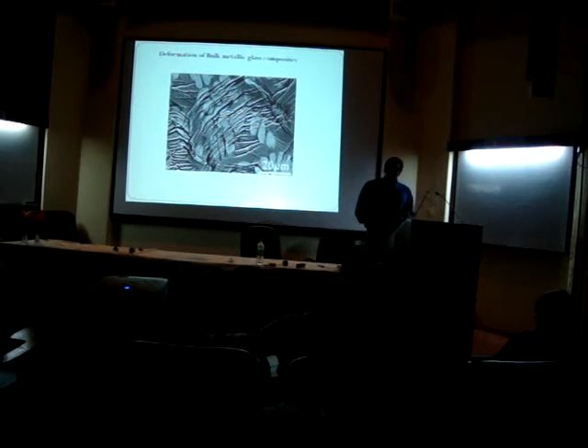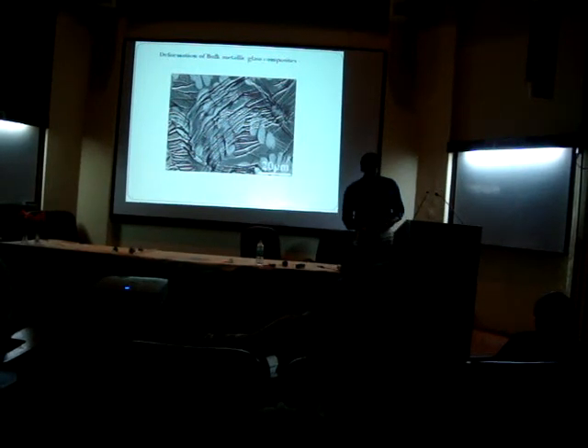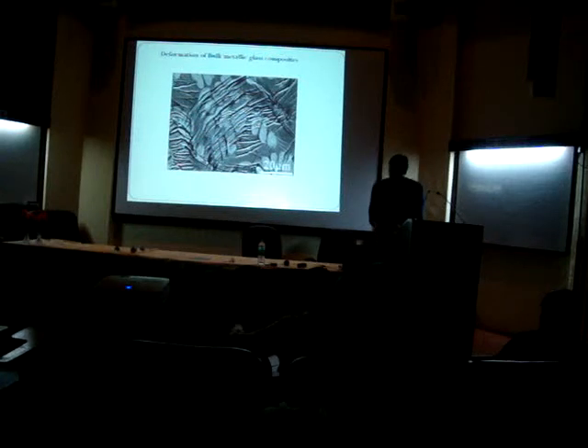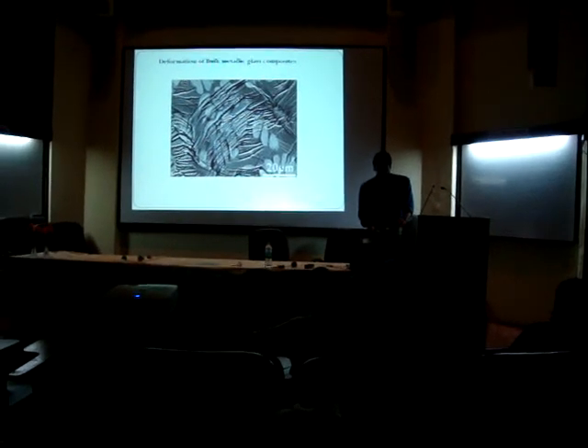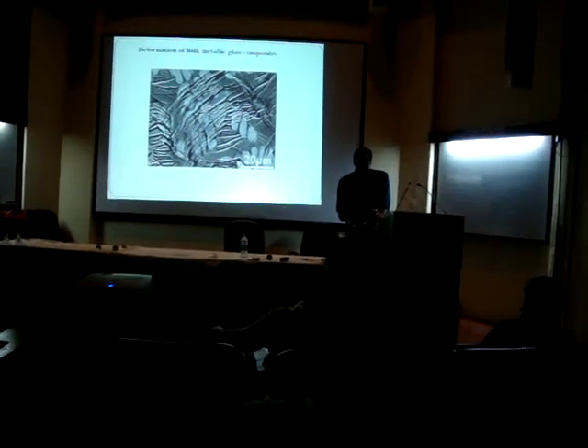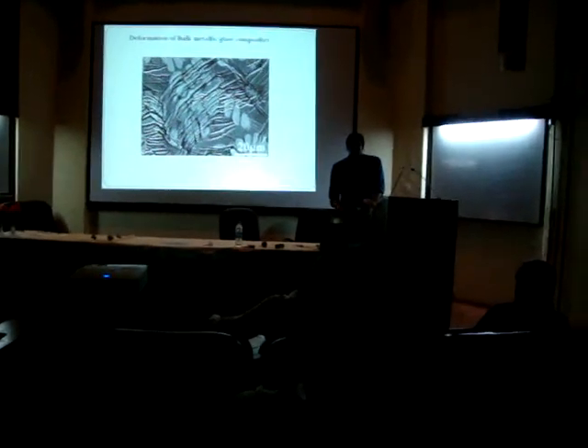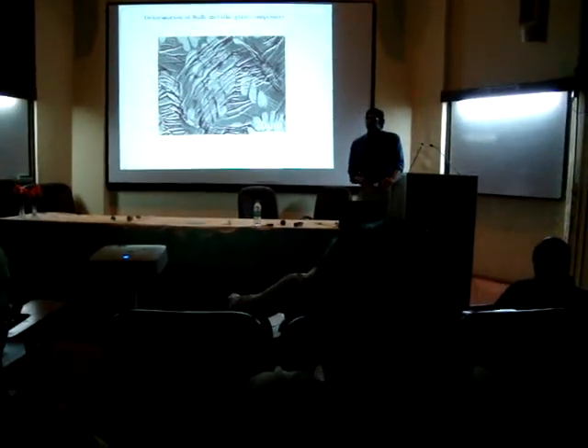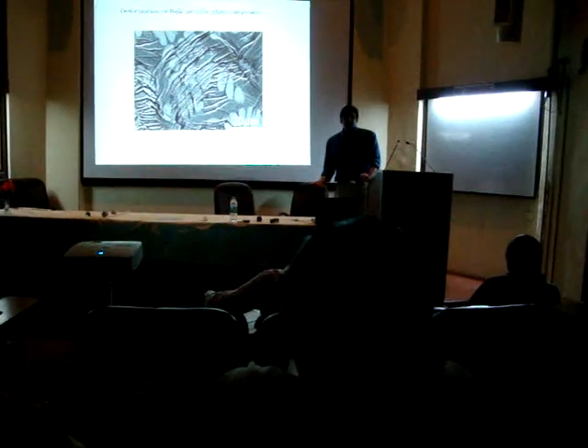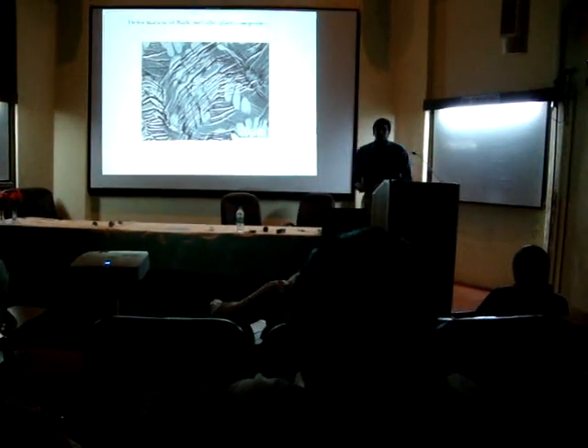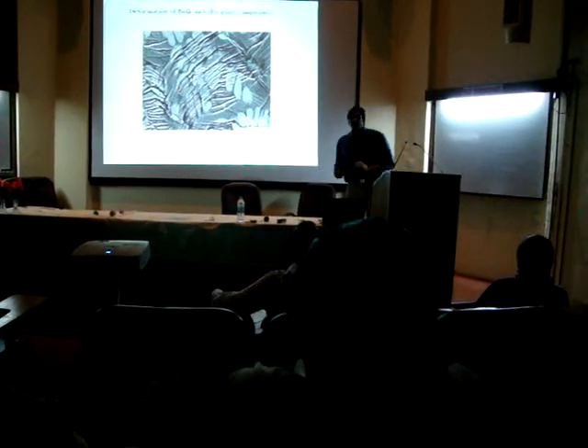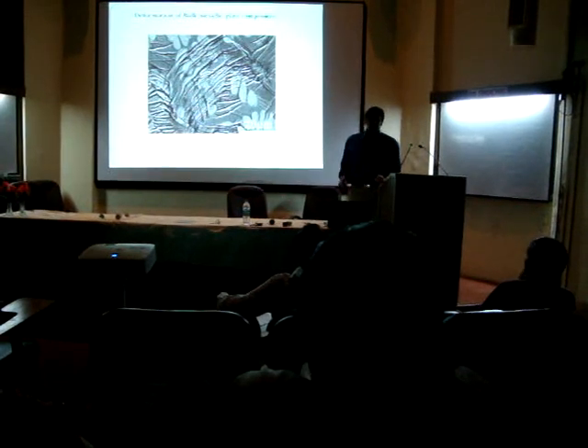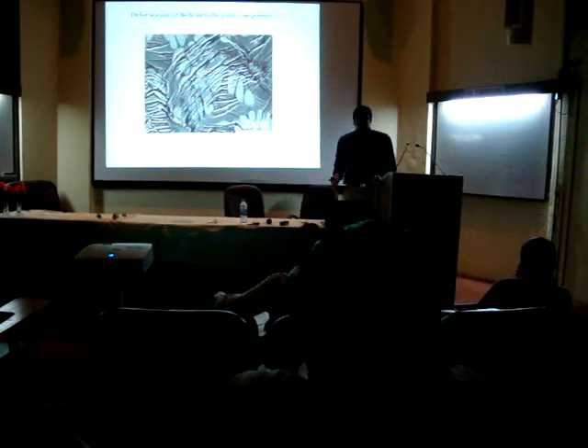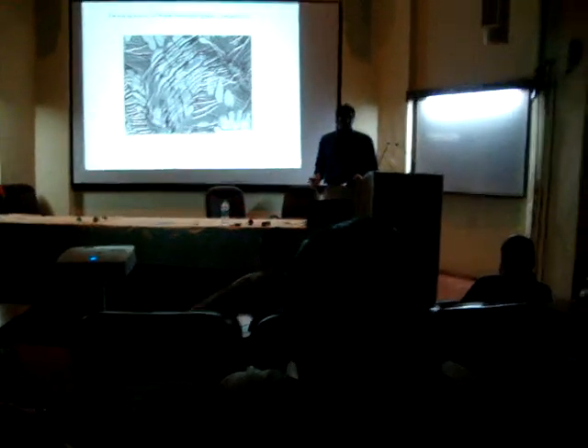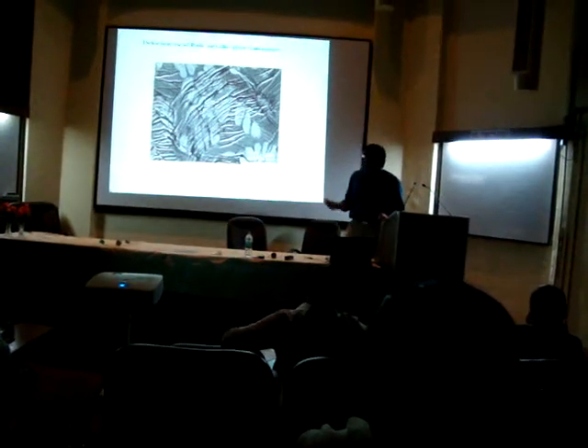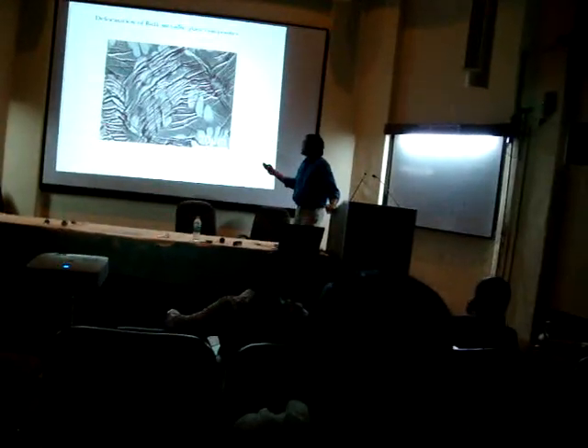Now, we move on to the last part of my talk, and I should talk about another way of toughening glasses, which recently became popular, where you introduce a second phase, a ductile phase, and this ductile phase promotes shear banding, which improves its tensile integrity. Earlier we saw that if you pull a BMG rod in tension, it will break catastrophically without any sign of ductility. But when you add a second phase, this can nucleate shear bands, deflect them, multiply them, and even allow them to work harden.